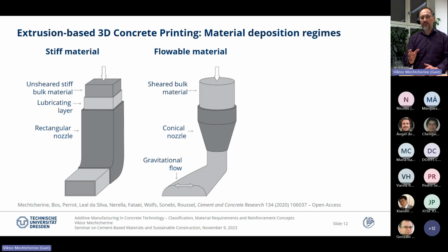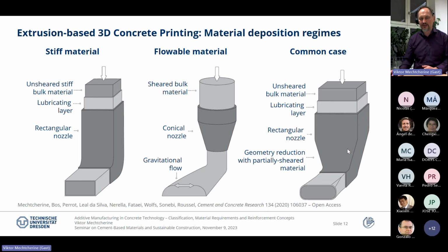And another case is that the material is flowable. Some accelerator is added at the nozzle, and eventually it will, of course, lead to stiffening of the material. But at the moment, we consider the situation that this action is not developed yet, and so we have gravitational flow. Both these situations can be described mathematically pretty well. What we found, however, in practice is often the common case where we have a little bit of flow, some deformation of the filament upon deposition, but not very much. This situation cannot be described by analytical formulas, but rather we would go for numerical simulation.